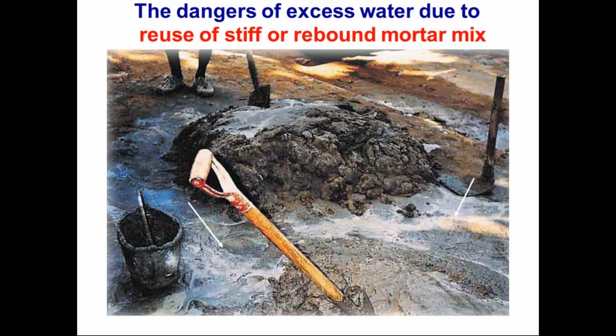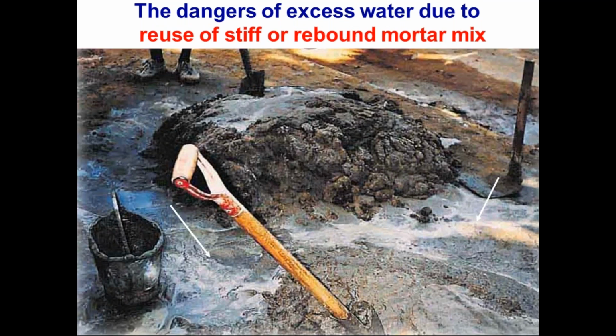Next. Another thing I have observed is the preparation of the mortar. The preparation of the mortar is done using large quantity of sand and cement, and the mix is done in such a manner that the mason is unable to finish the mortar within a matter of, say, 30 minutes. When it is not done, then they put more water on the half set plaster and again remix it. Sometimes they put some cement on it.